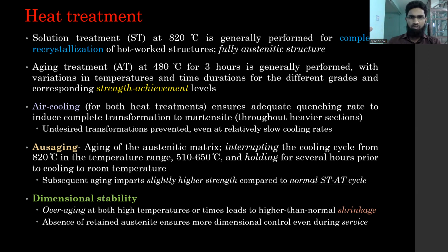So for specific purposes, this may be utilized. Ausaging and dimensional stability, which we have discussed already. Overaging, at both high temperatures or high time, leads to higher than normal austenite reversion. So overaging is something that is not desired. The aging schedule has to be set so that austenite reversion is not there, and this shrinkage issue is also not there.